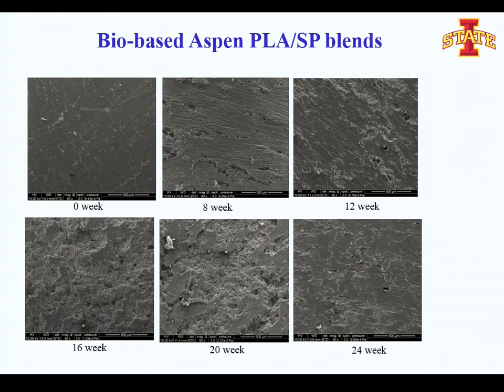And this is also the SEM, the morphology of the material. We have a very smooth structure. After just 8 weeks, we have a very rough surface with a lot of degradation. And after 20 weeks, you can see the first layer of the sample is totally degraded, and the sample becomes thinner. And this is probably here to get more smooth again, because the first layer of the sample is already degraded.